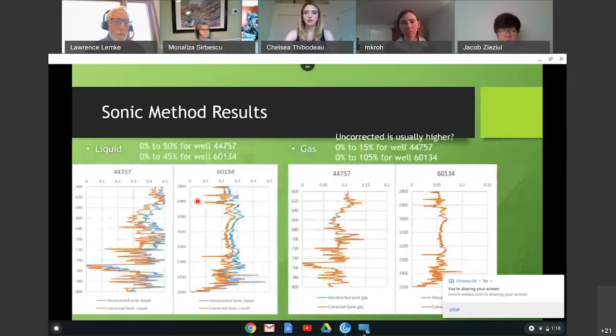The same method for the sonic, and already you can see that the sonic porosity method produces higher porosity results ranging from 0 to 50%, or 0 to 45% for a different well. And there are lower lows and higher peaks, and you can see more distinction between the members and their porosity values. So sonic is a pretty sensitive method.